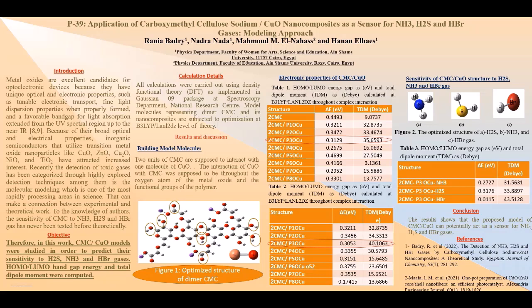Model molecules representing dimer CMC and its nanocomposite are subjected to optimization at the B3LYP/LANL2DZ level of theory. In building our model molecules, 2 units of CMC are supposed to interact with 1 molecule of copper oxide. The interaction of copper oxide with CMC was supposed to be throughout the oxygen atom of the metal oxide and the functional group of the polymer. Thus, as we can see from figure 1, the proposed structure of CMC contains 8 active sites.